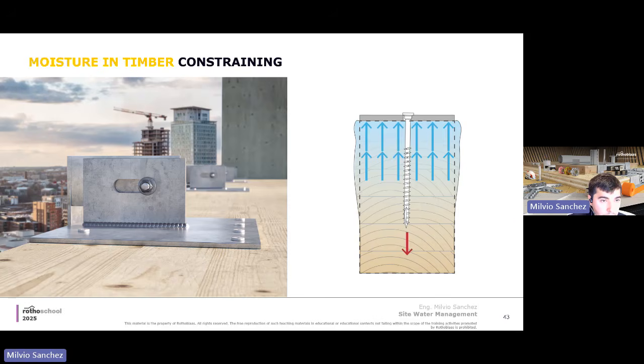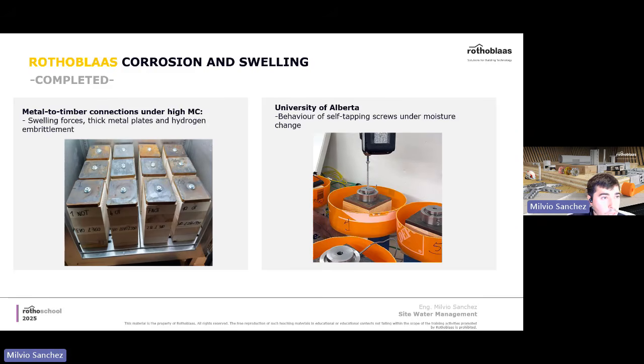And this is something that for sure, most of the time, is not considered and not assessed during the design phase. So this is a critical unintended force due to swelling that may happen on the job site as well. In other research campaigns that we have completed on this topic, we assessed thick plate with CLT as well under high moisture content. We analyzed the swelling forces, thick metal plates, and hydrogen embrittlement as well, all of these effects.